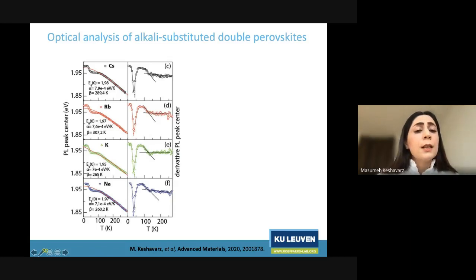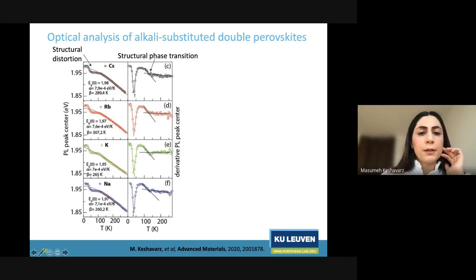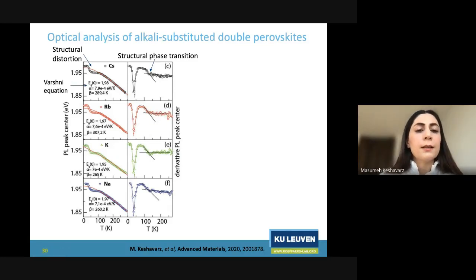more or less. And we confirmed through dilatometry measurements and also high resolution XRD measurements that these are actually phase transitions. And also at low temperature, we see a structural change, which we couldn't confirm through XRD measurements, and we think that this is just structural distortion and not a phase transition. And these are fitted with Varshni equations and the parameters extracted.